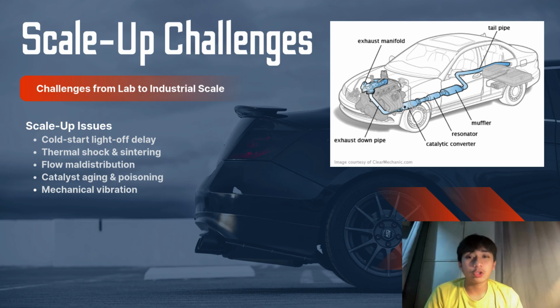When scaling from laboratory testing to the automotive system, additional challenges arise. For scale-up challenges, first is cold start performance. Catalysts are less active at low temperatures, leading to delayed light-off and higher emissions. Second, strong exothermic reactions can cause thermal shock and noble metal sintering, reducing catalyst lifetime.